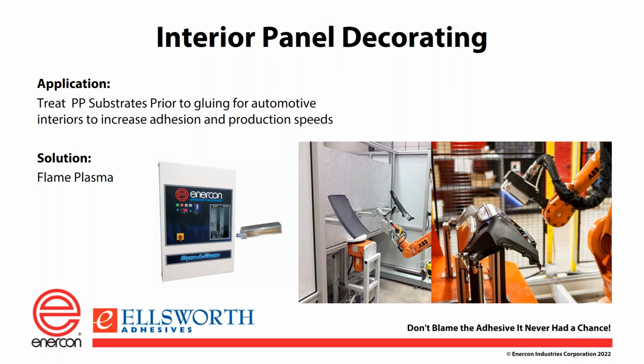Another is interior panels for cars: dashboards, side panels. They're almost always done with flame, and the reason again is the multi-dimensional surface. You can see the dashboard on the far right there and the flame trying to treat that. There's a lot of convex and concave areas on that, so treating that with the flame is very fast. You can do it in just a few seconds, and you get a good consistent treatment on there before they put the decorative coating on. And then of course you see the door panel a little bit left of that. This is the flame solution, but then they would put the adhesive on and then whatever decorative coating you're going to have in that type of vehicle. That's usually a polypropylene, or sometimes it's a fiberglass dash or door panel.